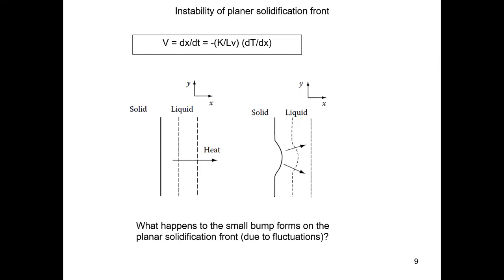So this means that this planar growth scenario is probably going to work in the beginning stage of the nucleation and growth, especially the initial stage of growth. But it won't be dominant in the full stage of growth, right? As you see in most cases, as the snowflake grows larger and larger, you see a lot of these branches forming, these dendrites forming, right? So this means that instability is going to kick in at some stage of the growth process and take over and become the dominant mechanism for the growth. Okay, so that's just what we can analyze now.